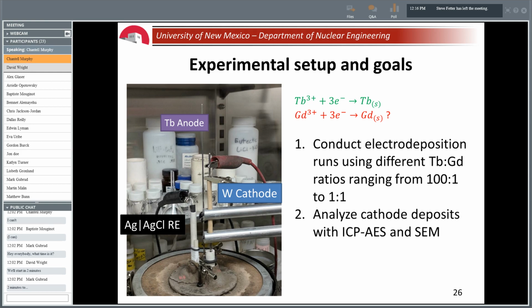Here's a picture of the 3-electrode setup I have in the furnace, where I'm using a 5 mole % silver chloride reference electrode. All of the potentials are in reference to that reference electrode. The anode consists of a 6.35 millimeter diameter terbium rod, and the cathode is a 2 millimeter tungsten rod. The experiments, storage, and handling of all chemicals are carried out in a glove box with an inert argon atmosphere. The goal is to operate the cell to deposit terbium on the cathode. I ran 8 different experiments, as you saw from the previous chart, increasing the amount of gadolinium in order to see if that would also reduce.